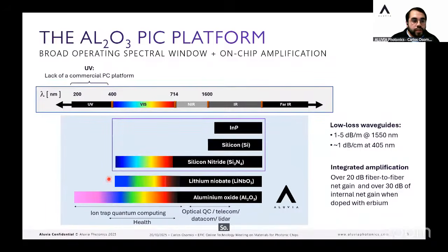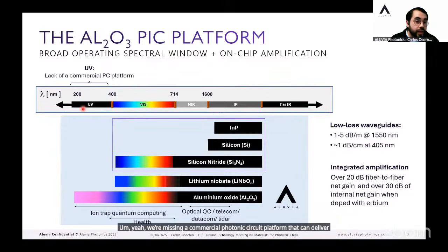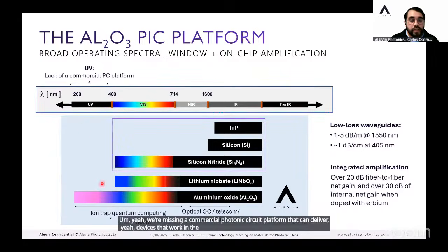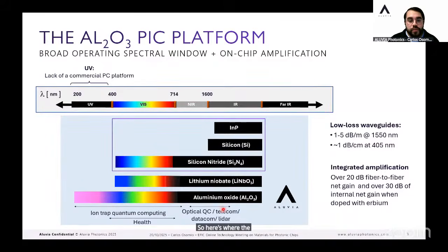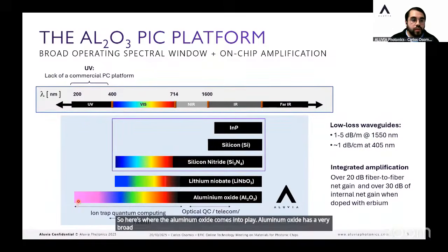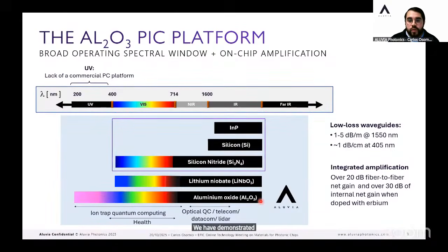Here we show the transparency window of all the material platforms, and we see that for the other material platforms, we're missing a commercial photonic circuit platform that can deliver devices that work in the UV range. So here's where aluminum oxide comes into play. Aluminum oxide has a very broad transparency window, all the way from 200 nanometers to the mid infrared. We have demonstrated very low losses in waveguides.